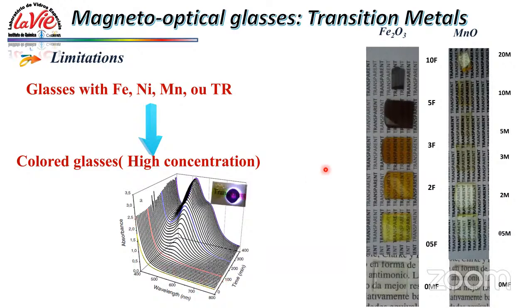However, when you try, for example, to thermally treat this glass, or what we were intending in this case, to put this glass in the form of optical fiber, it changed color. So you need to protect the drawing atmosphere using argon or nitrogen to avoid the oxidation of manganese, which in this case passed from manganese 2 to manganese 3. So we have here a charge transfer absorption, and the glass becomes very, very pink, dark.